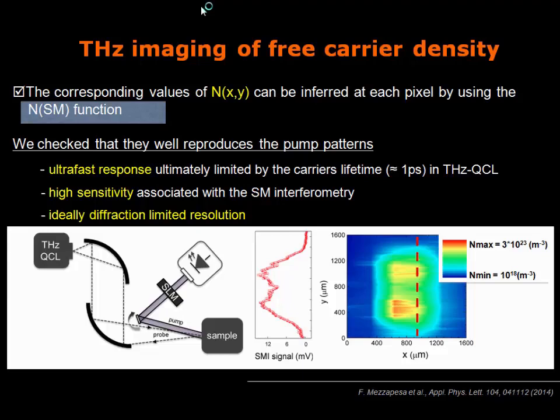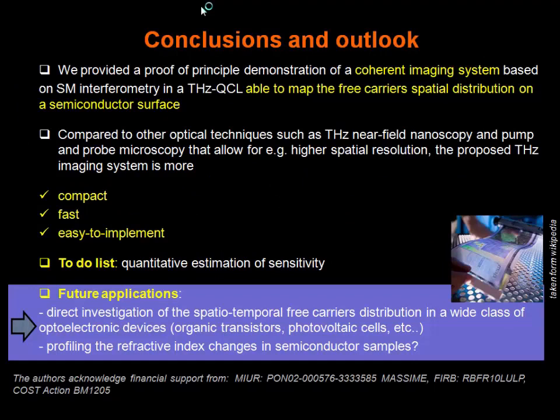We want to underline that the response is in principle ultra-fast, because it is limited only by the carrier lifetime, which in semiconductors is around one picosecond, making this a very fast sensor. We also benefit from the high sensitivity intrinsic to the self-mixing technique, which is an interferometric technique. The spatial resolution is ideally limited only by diffraction. In conclusion, the goal was to provide a proof-of-principle demonstration of a coherent imaging system able to map the local distributions of free carriers on a semiconductor surface.